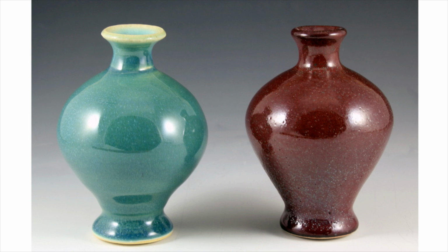Another factor is the firing atmosphere. These two bottles have the same glaze. One was fired in an oxidizing electric kiln and the other in reduction. Both were fired to cone 6.